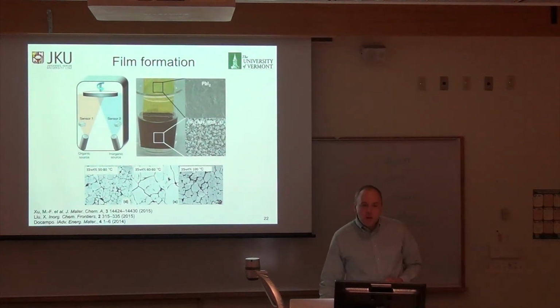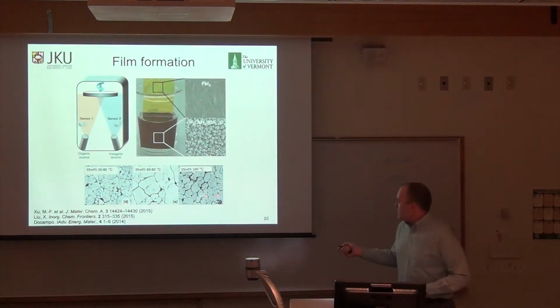So why does a film crack in general? It doesn't necessarily crack. It's just that as you grow, certain peaks start to form, and then they are growth sites for the next layer. So as you're putting down the next layer, it will preferentially stick to the tallest thing, giving non-uniform growth. And you have mobility if you're coming from solution—everything's mobile, and it will just stick together into these tiny salt crystals, and then those will grow. So rather than making a continuous film, you get something that looks like this.